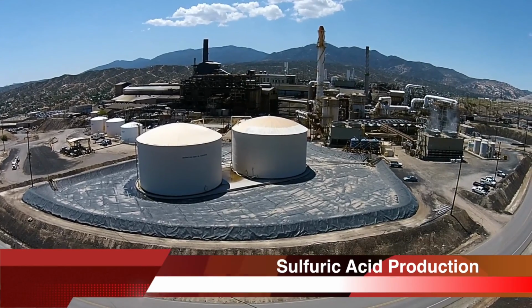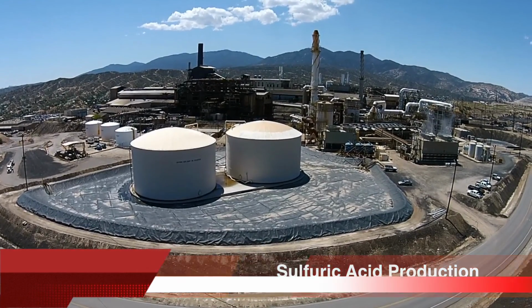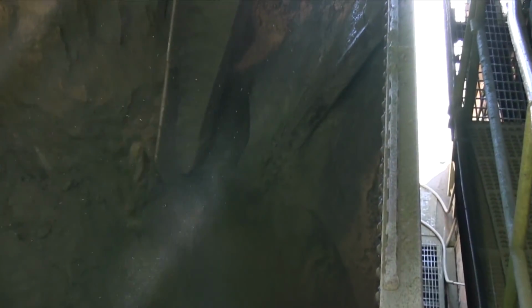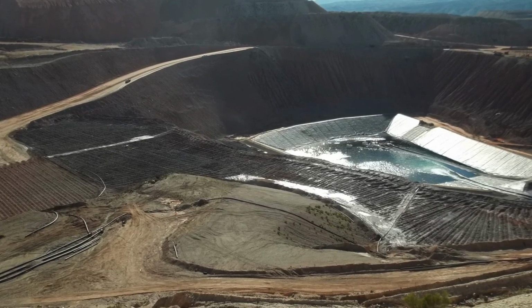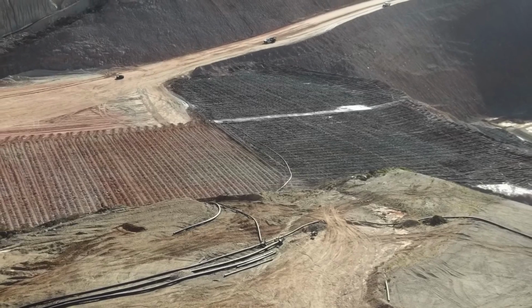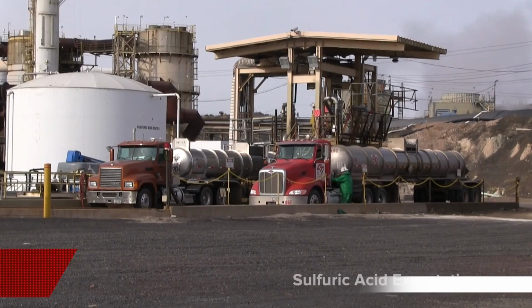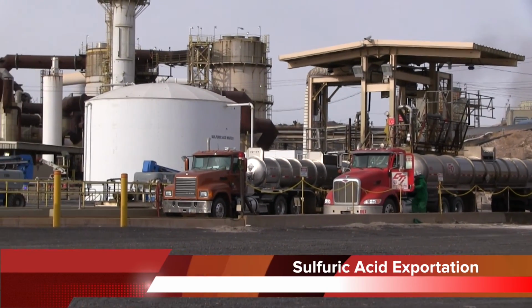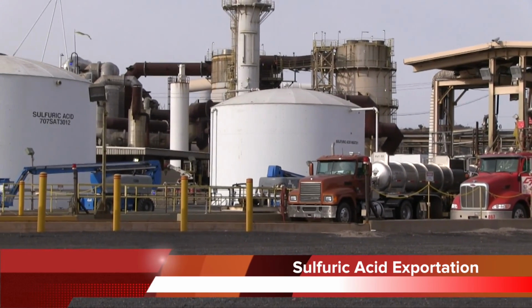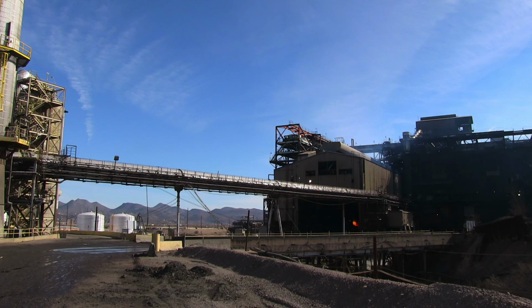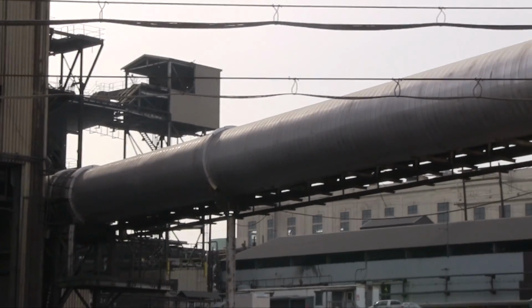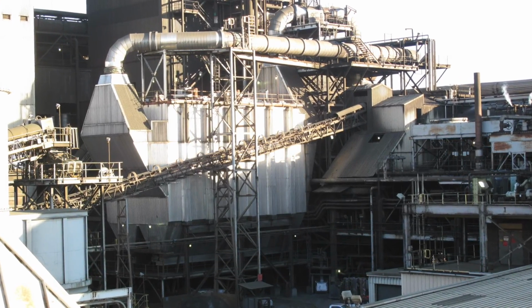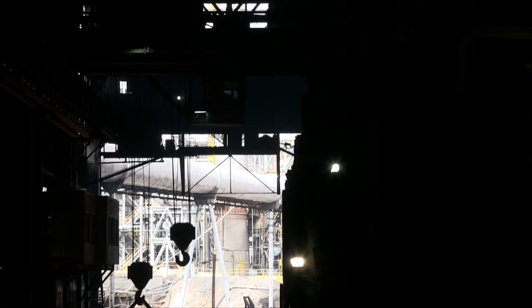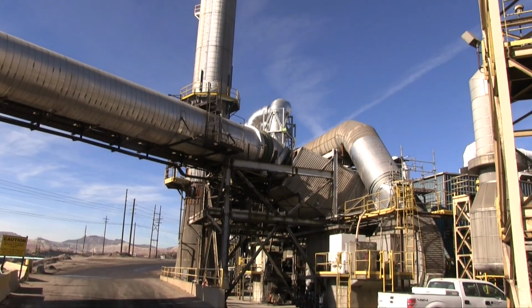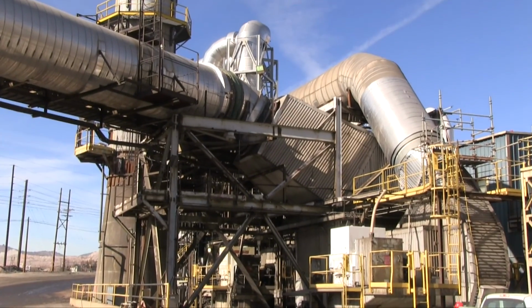The acid plant is an extremely important part of our business, producing sulfuric acid by capturing the sulfur naturally contained in the copper concentrates. Our sister properties depend on our sulfuric acid to leach the copper from the ore mined at their sites. We ship approximately 100 truckloads of acid a day, and each truckload holds 26 tons of 95% pure sulfuric acid. The acid plant makes the sulfuric acid out of the gases captured from the electric and ISA furnaces and the converter. For each ton of concentrate we process, we produce 1 ton of acid. The Miami smelter captures 98% of all the sulfur contained in the original concentrate.